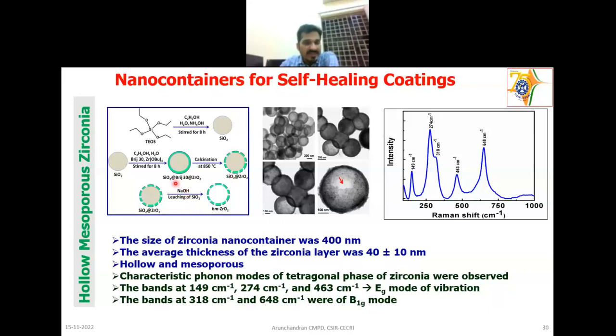Now what you are doing is NaOH treatment. Silicon dioxide is easily soluble in NaOH, so the silica will move out. So the core is removed, and a hollow mesoporous zirconia you got. So this is zirconia nanoparticle, and the container size was around 400 nanometer and the shell thickness was 40 plus or minus 10, and this we characterized also.